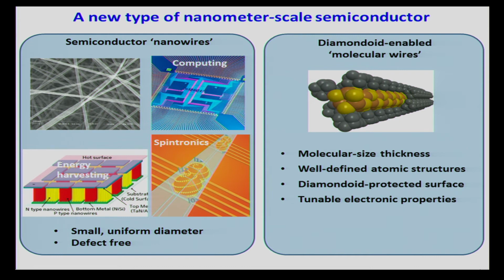And by using different diamondoids and different, let's say, metal species, we can tune the electronic properties to suit different needs. And this is really, again, enabled by having the diamondoid as a non-bonding tuning factor to control the structures of the growth of these molecular wires.